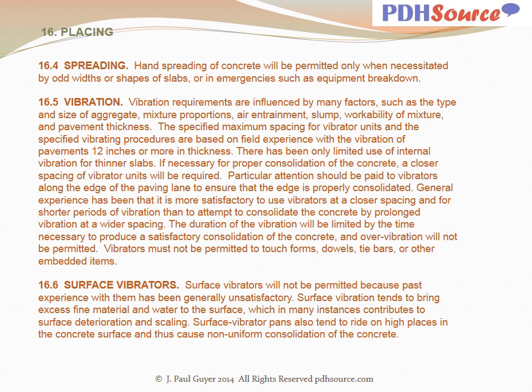Surface vibrators will not be permitted because past experience with them has been generally unsatisfactory. Surface vibration tends to bring excess fine material and water to the surface, which in many instances contributes to surface deterioration and scaling. Surface vibrator pans also tend to ride on high places in the concrete surface and thus cause non-uniform consolidation of the concrete.